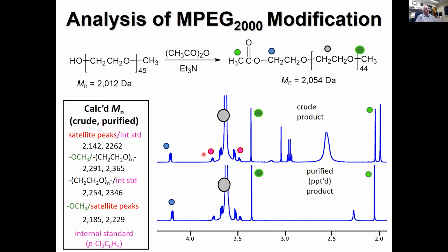We see that the crude polymer here, which still has some triethylamine and other junk in it, has a slightly lower molecular weight than the purified polymer, but that's expected because the purification involves a fractionation. Now, this chemistry works reasonably well for PEGs.